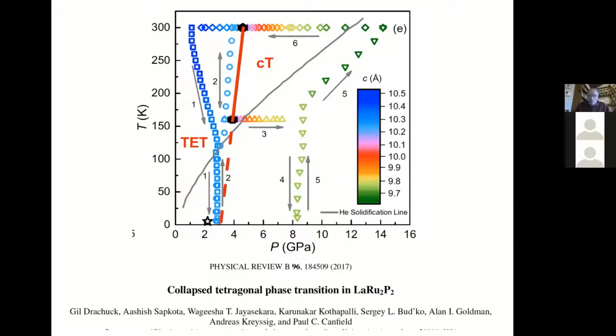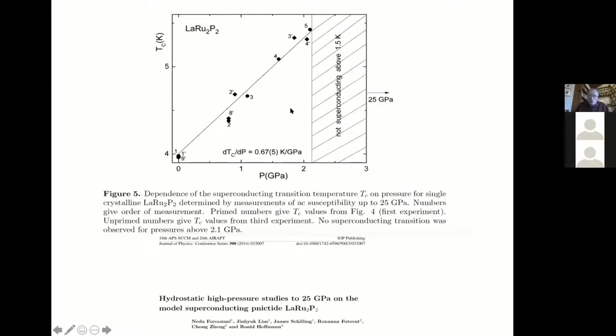And this work actually followed on earlier superconductivity work done by Schilling, and actually Hoffman's a co-author on this paper, that this is a 4 Kelvin superconductor. Again, this is in the long phosphorus distance. And with pressure, superconductivity increases as you go towards making this distance shorter, but it collapses into this collapsed tetragonal structure and superconductivity disappears, sort of following this trend that we saw earlier in those lower TC materials.